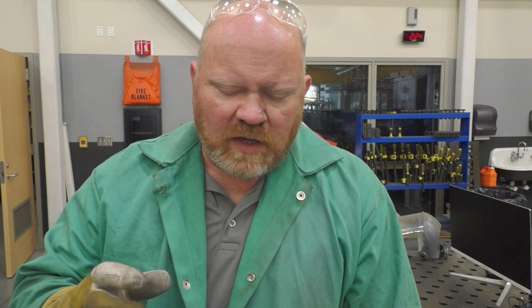The corner of a fillet is going to be harder to penetrate into than a butt weld. AWS test, you have a 45 degree included angle. On a fillet weld, you have a 90 degree included angle. So it's half, but you have a quarter inch root opening and a backing bar. So it's pretty easy to penetrate into that corner. Plus you're welding into a plate that's been beveled, so you're melting a knife edge, okay? You're melting almost nothing away. That fillet weld can be a challenge to dig into.